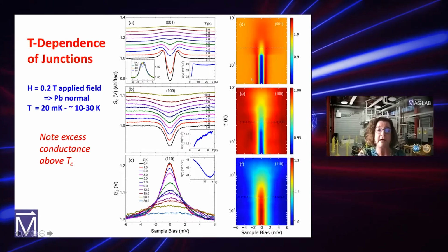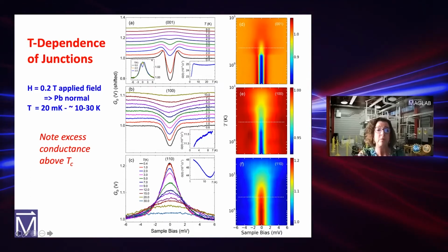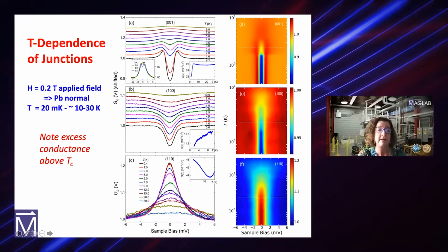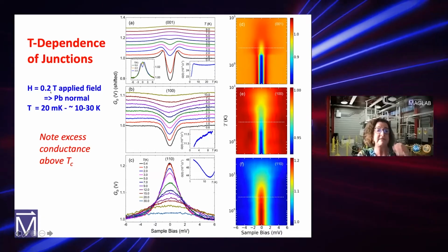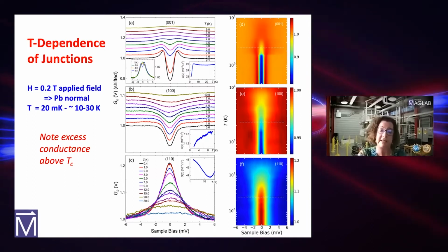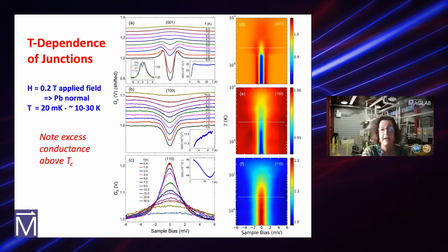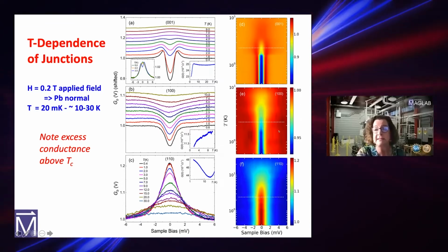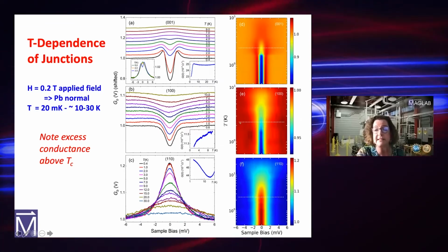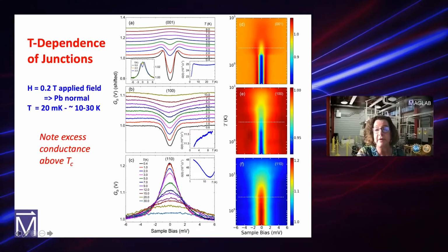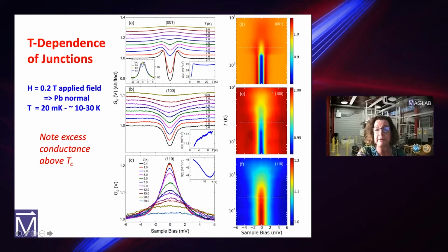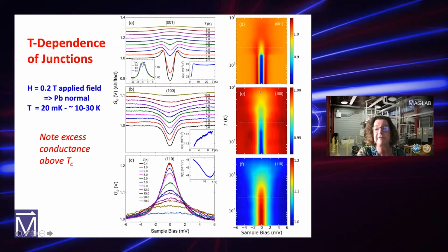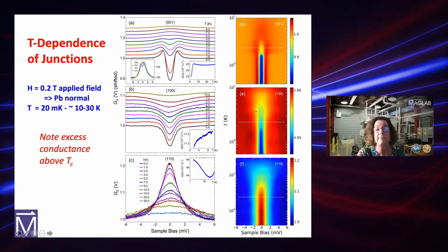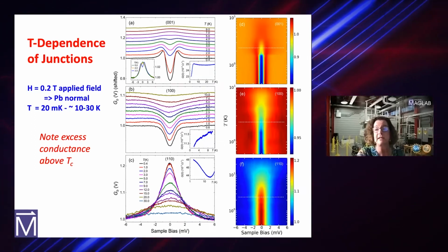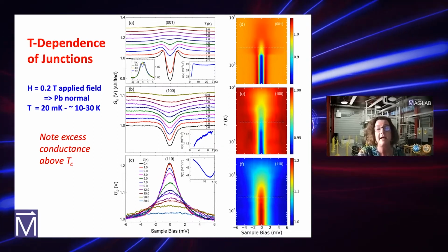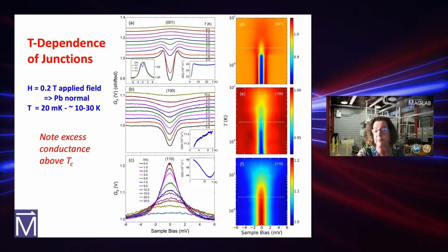What we have here is the current voltage where the only field is 0.2 Tesla, 2 kilogauss, which is very, very low for CeCoIn5. You need several Tesla to drive these things to get Hc2. All we want to show here, if we look at these color plots, is that this line here is where Tc is, okay? And if we go up in temperature, we see that there's stuff going on above Tc. Without spending a lot of time, we're in agreement with previous measurements that show that there is pair potential above Tc, and we have identified those as definitely preformed pairs.